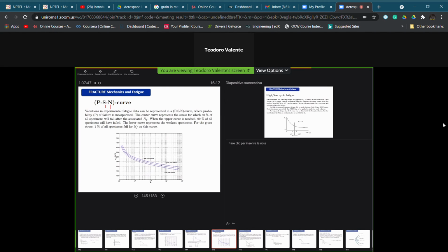But you can also have available, for the same materials on the same Wöhler diagram, different curves to which we can associate different values of probability of failure, and then use the curve which fits our purposes, for example on the basis of a risk analysis or of indications that we need to respect because they are standardized.